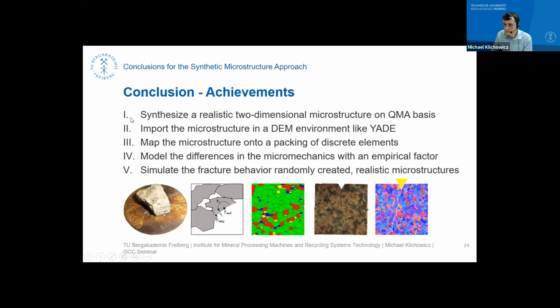So let's have some short conclusions. We are able to synthesize realistic two-dimensional microstructures on this QMA basis, which is some sort of image analysis. We can import the microstructure into a DEM environment. Here I used Yade, for example. We can map this microstructure onto the packings of the discrete elements, and we can model the differences in the micromechanics with an empirical factor that was just presented here in the outlook.